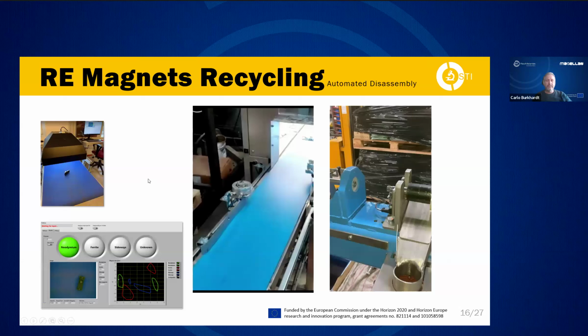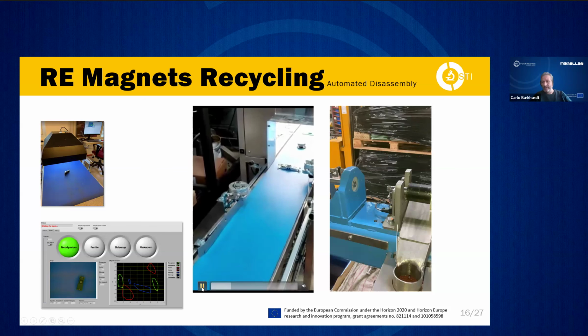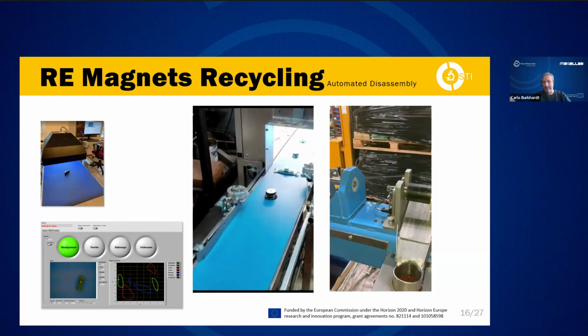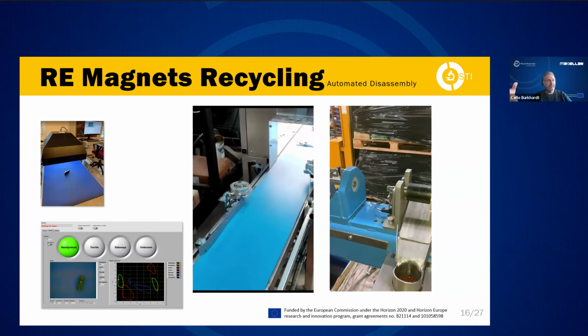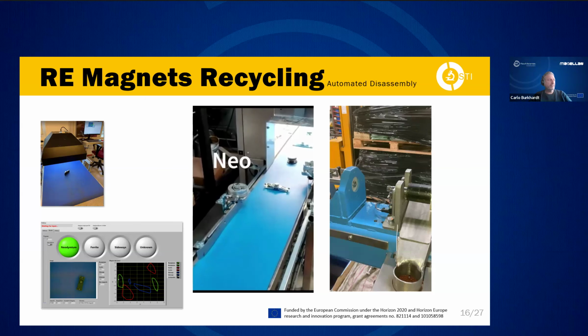Another value stream that we looked into is the flat screen TVs. Flat screen TVs, again, would have a magnetic content that's not viable for recycling, but you have to open the flat screen TVs anyway to get out the TFT screens because of the mercury. And then because they're open, you can extract easily the loudspeakers that contain the magnets. And here we have ferrites and we have neodymium iron boron, currently about 50-50 ratio. The flatter it is, the more neodymium iron boron will be in, so increasing with time.